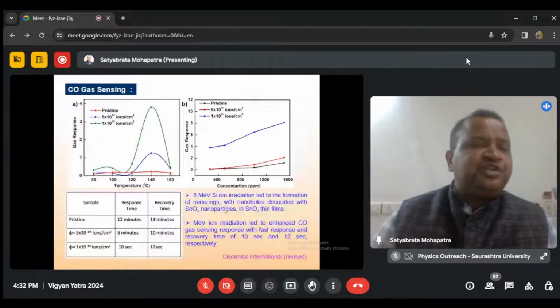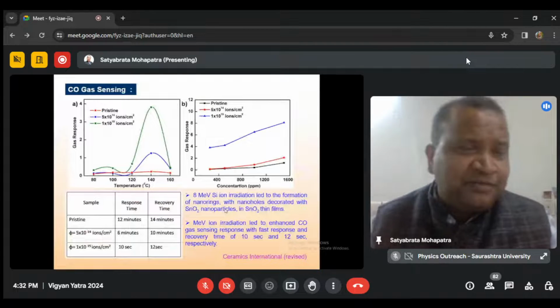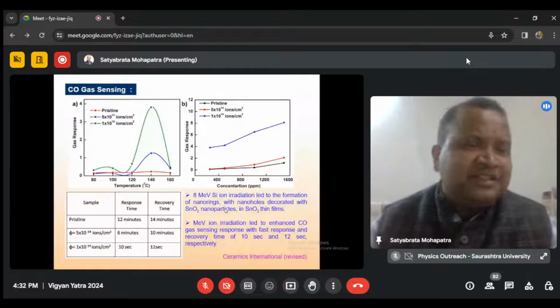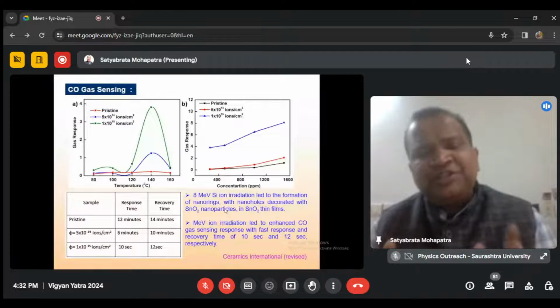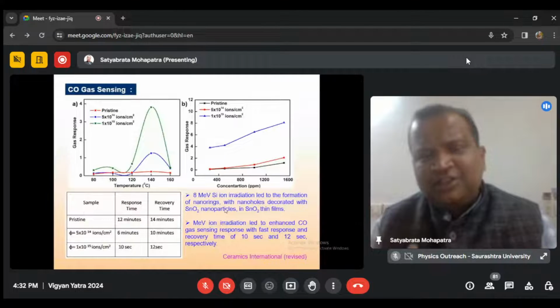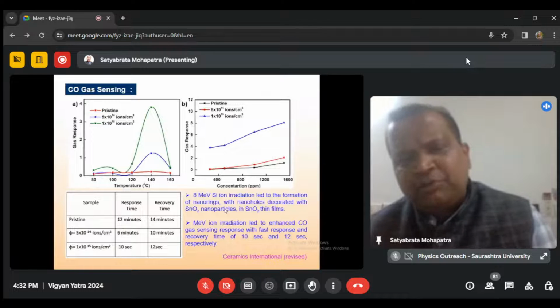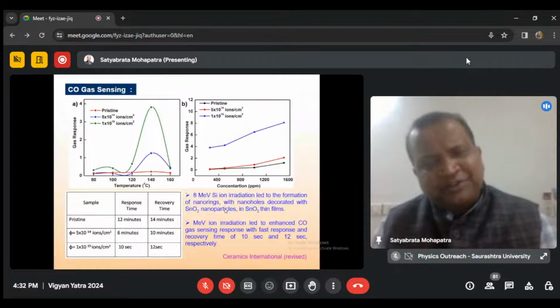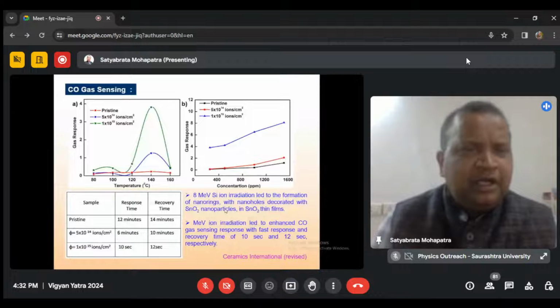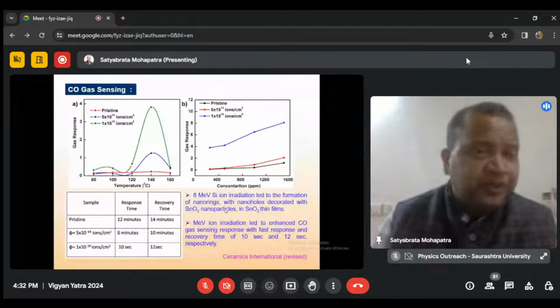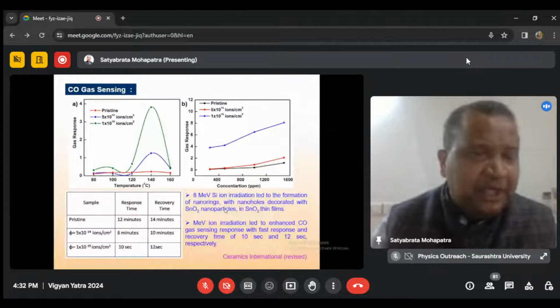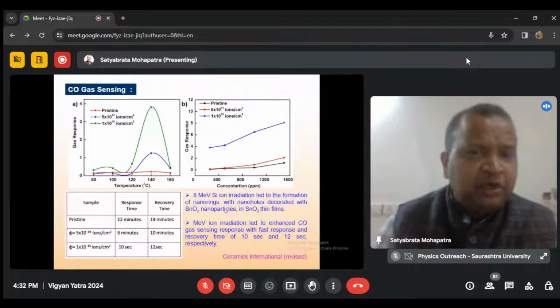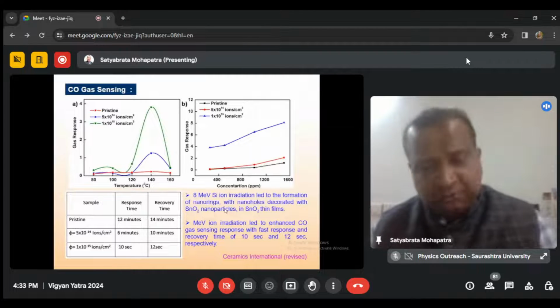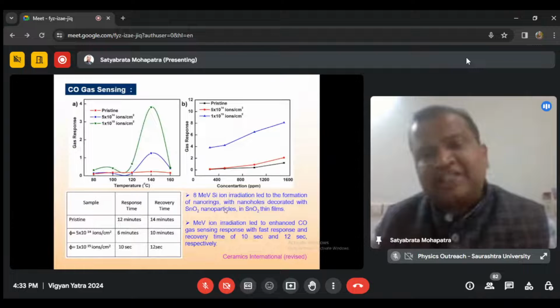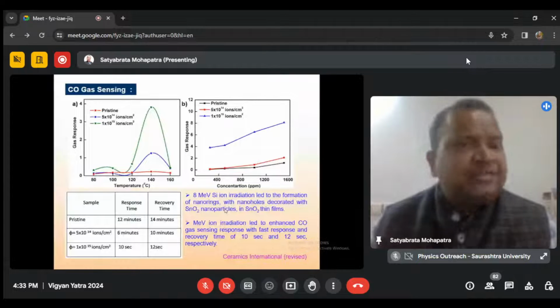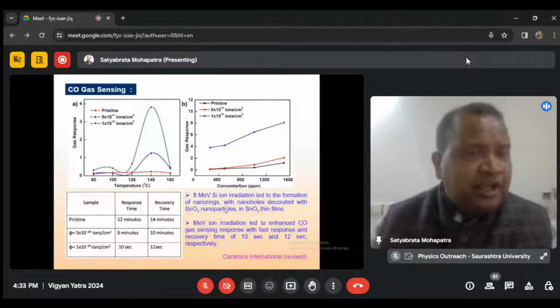Now we wanted to see whether this is beneficial for carbon monoxide gas sensing. You can see that this is a very simple technique. Just deposit a film by simple thermal evaporation, and expose for a very small time. And if you can improve the sensor response, nothing like it. It's a film which is scalable, which you can deposit over a large area, as many as you like at one go. And hence, this is beneficial if it is leading to an improvement, and it does.